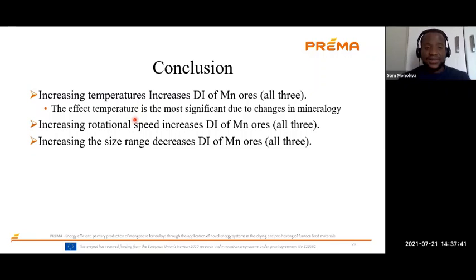Then we have the increase in rotational speed, which increases the DI as you mentioned. We increase the frequency of collision between the particles and each other, and we increase the frequency of particles colliding with the walls of the container, hence increasing the DI. Then increasing the size range decreases the DI of Mn ores, which is mainly due to a reduction of the number of particles as the size range increases, and also a reduction in the area of contact between the particles and the walls of the container when the size range increases.